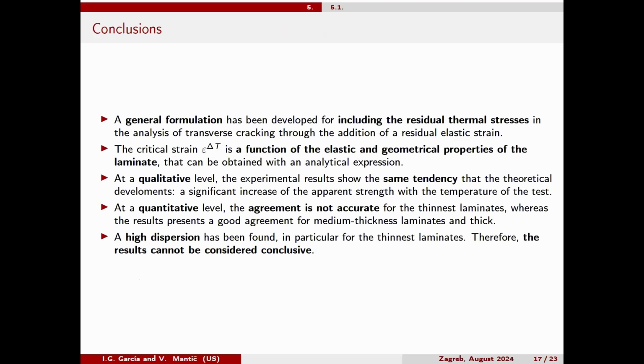So to conclude, we have developed a general formulation to introduce the effect of the residual thermal stresses, and this formulation is very easy to apply to all the models that are the most popular in composite. It's just to add a term to the strength that we have mechanically. We have compared that with the experiment, with some preliminary experimental campaign. At a qualitative level, the increasing tendency is predicted well, but at quantitative level, the predictions are not good, and we need more experiments to verify this is correct, and or if we need to take into account other kinds of phenomena in our strategy.